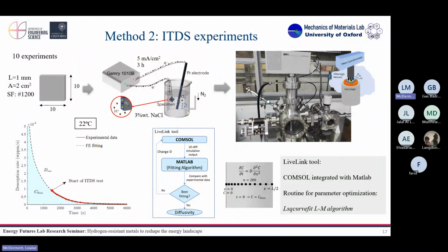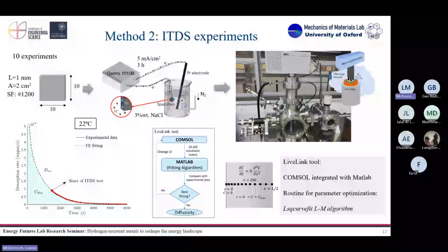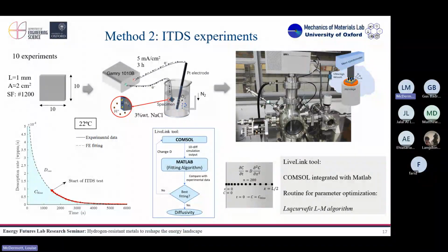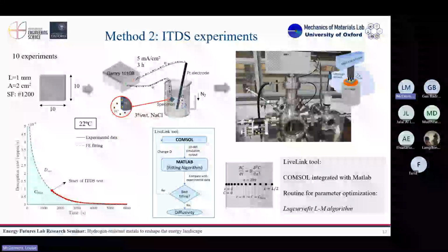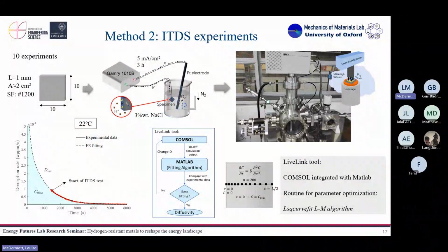Then you take your sample and put it inside this machine. It's a mass spec, an ultra high vacuum mass spec, so it operates at pressures of the order of 10^-9 millibars. Basically, the only thing you detect is hydrogen. You leave the sample inside and keep it at a constant temperature, the same as we did in permeation. In this case, it's room temperature.